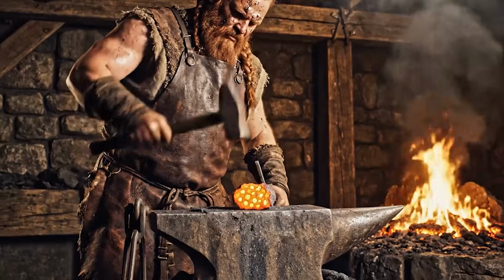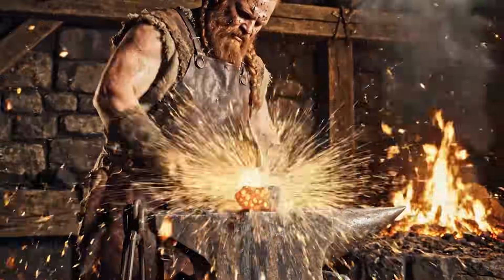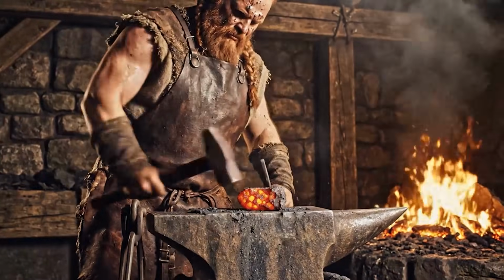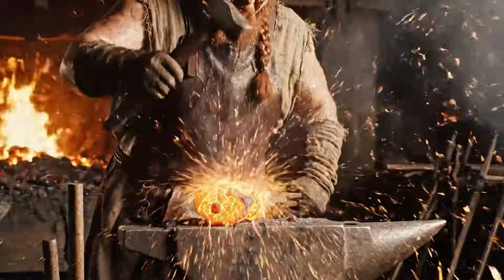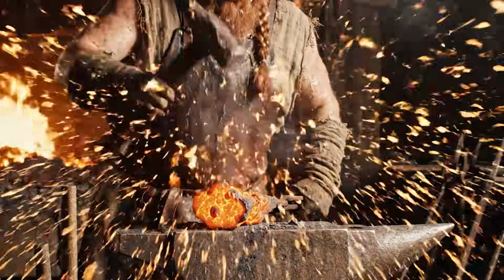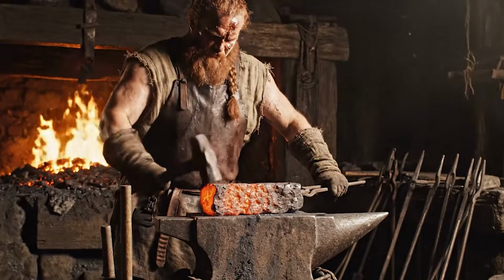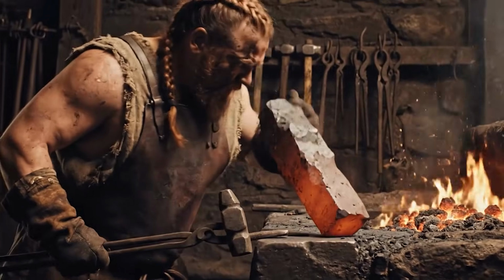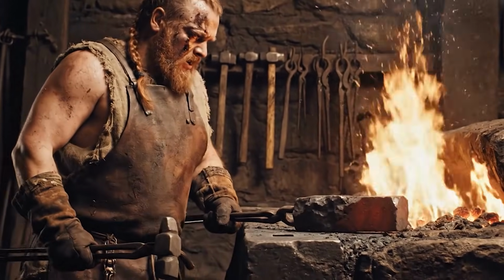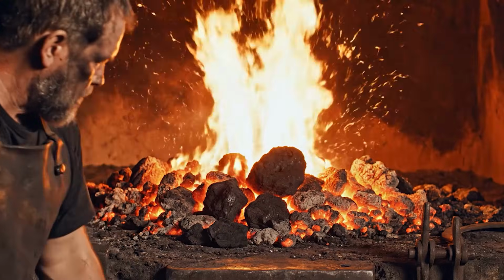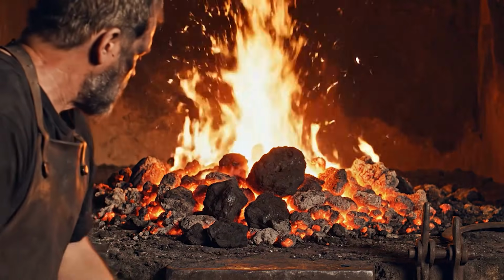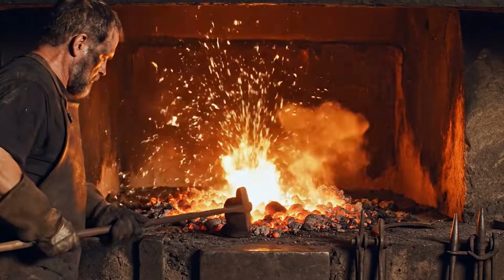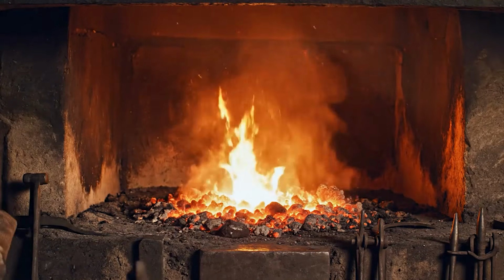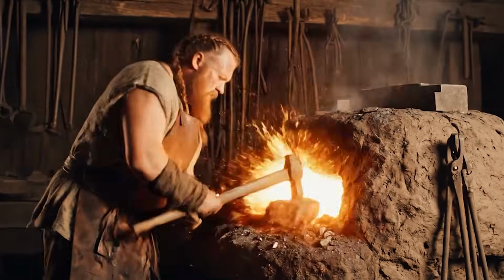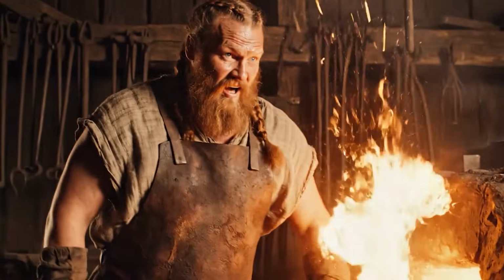This process was not only spectacular, but also critically important. The more slag that could be knocked out at this stage, the cleaner and higher quality the metal would be. Gradually, under dozens of powerful blows, the porous bloom became denser. It lost its spongy structure, turning into a more monolithic, though still very rough, bar of metal. This bar could already be considered pig iron, but it was still a long way from steel.